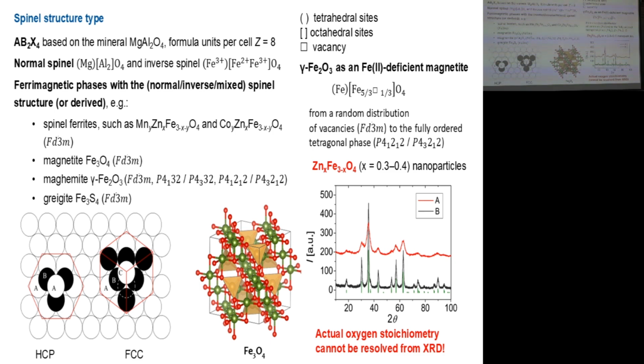And you will see thousands and tens of thousands of research articles where someone measures an XRD pattern, compares that with the PDF database, and will claim, okay, this is magnetite. But typically, it won't be magnetite. Typically, it will be some non-stoichiometric phase between magnetite and maghemite, partially oxidized to maghemite. But some people tend to conclude based on XRD patterns, not seeing some special features of the fully ordered maghemite, that it is not maghemite, that it is magnetite. So unfortunately, the literature is really flooded with wrong interpretation of XRD patterns.